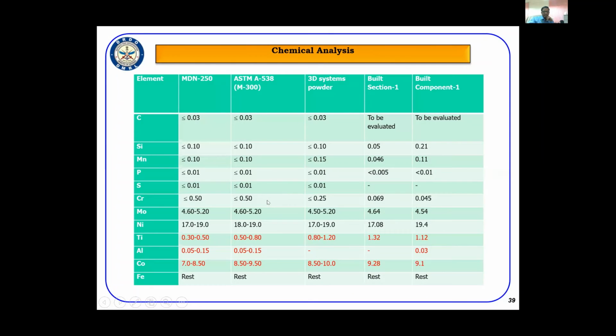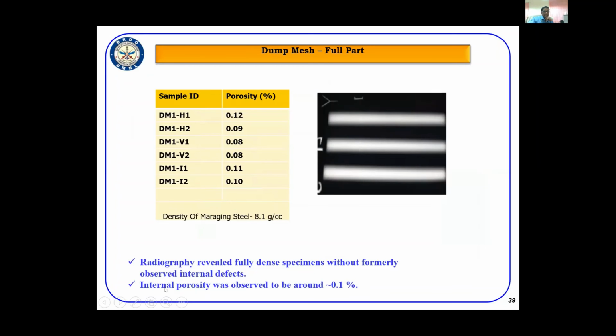Again, the chemical analysis has been carried out, which is meeting to the maximum extent, and the radiography again from the next build, the specimens have been subjected to the radiography, which has revealed very good dense material deposition without any internal defects, and the internal porosity was observed to be less than 0.1%. That means 99.9% dense material deposition has been carried out in this next run.